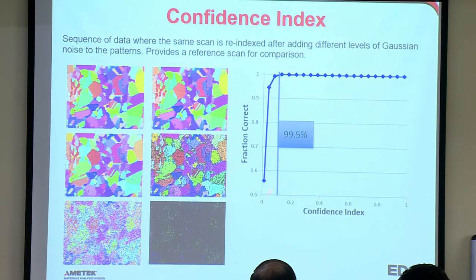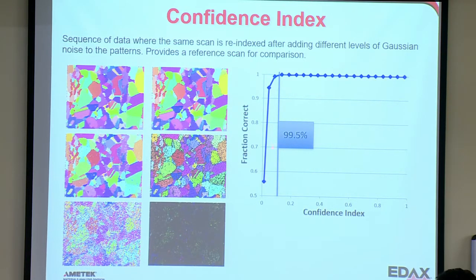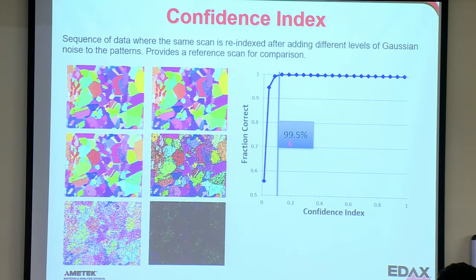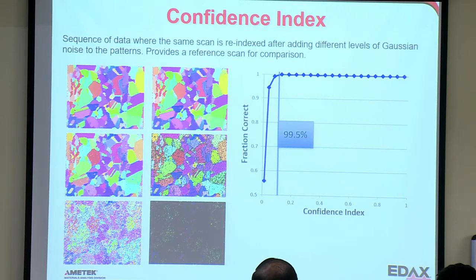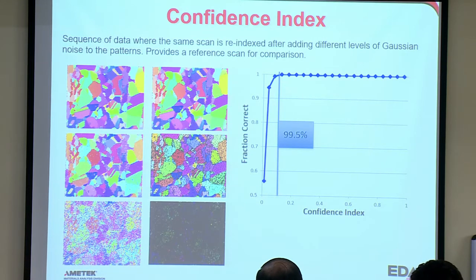So you can see when the confidence index is 0, we're actually still above 50% correct indexing. But if we go to a higher confidence index, as I get to 0.1, in this case, it's about 99.5% correct. This one's a little stronger than usual. I've done this with a couple of different materials. And generally, we find that if we're at about 0.2, we're usually around 99% correct. So if you're doing a scan and you get a confidence index of 0.2 on average, it doesn't mean you throw away your data, okay? Look at it closely, and I'll bet that probably 95% of it's good data. So a confidence index of 0.2 and above usually means we're almost near 100% correct, if you will. Although with a multi-phase sample, this will probably shift a bit.